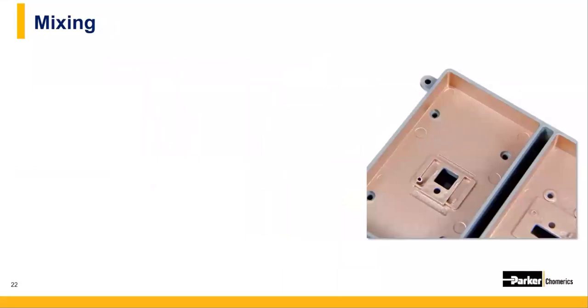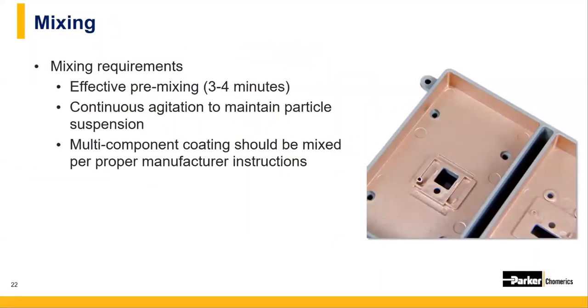One of the biggest and most significant differences in working with conductive coatings versus non-conductive coatings is the proper mixing of materials. Because conductive coatings consist of very heavy metallic particles suspended in a solvent and polymer base, the paint needs to be mixed on a paint shaker for at least 3 to 4 minutes before spraying.